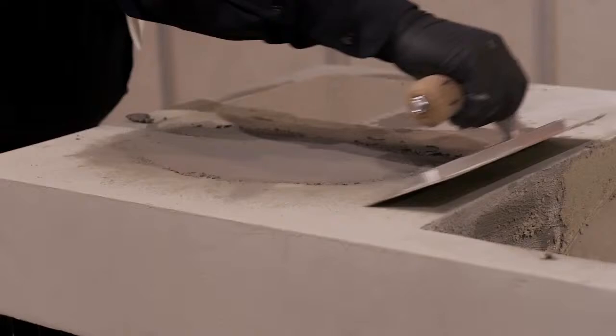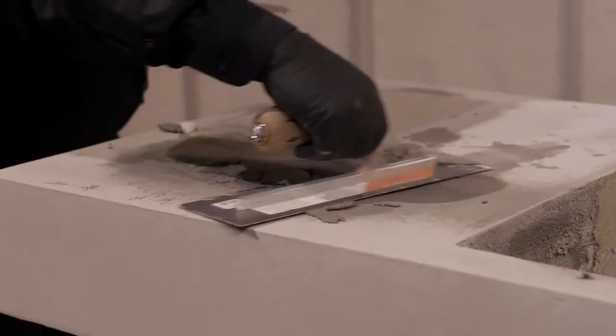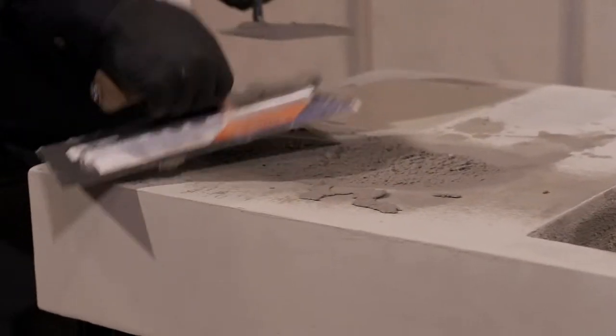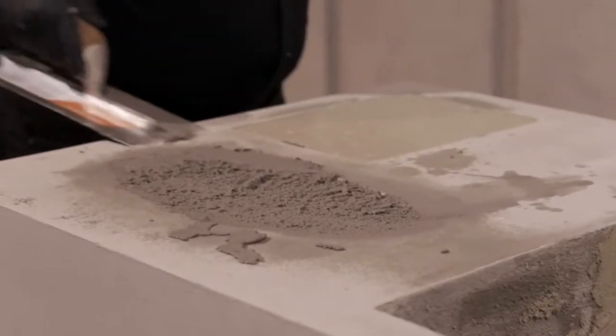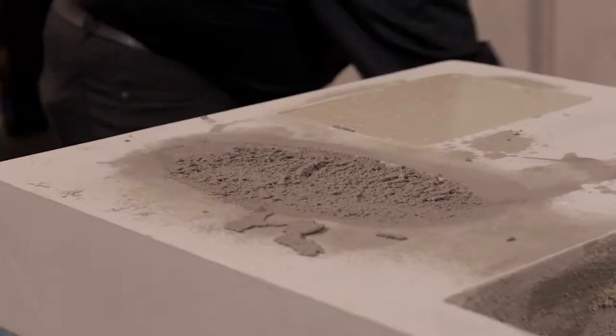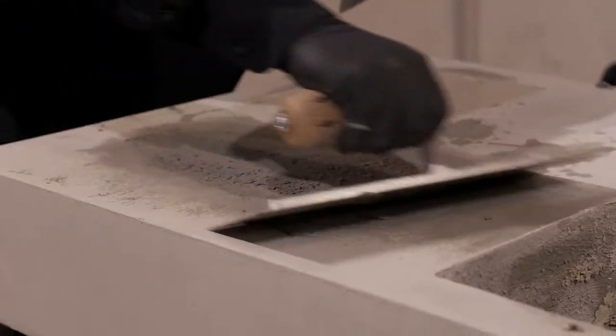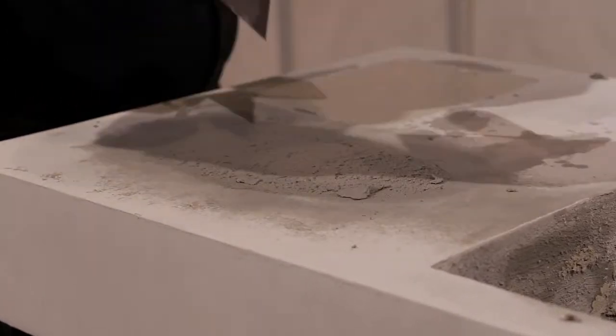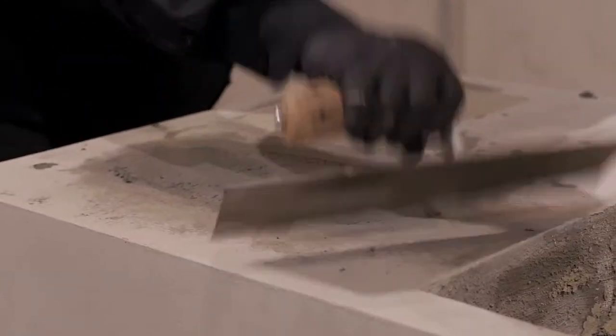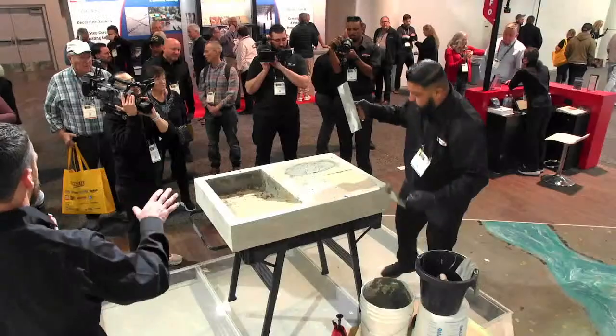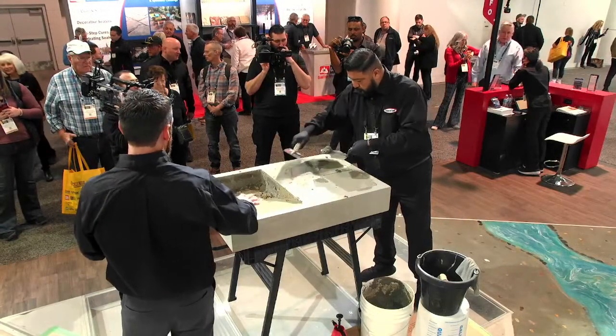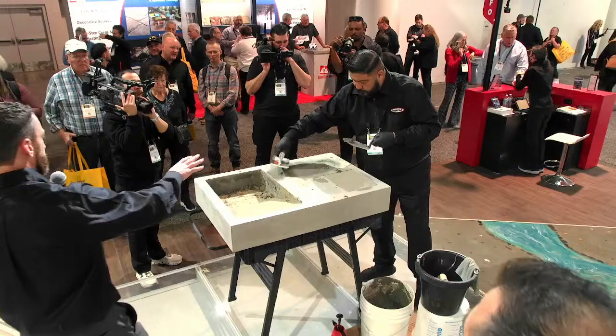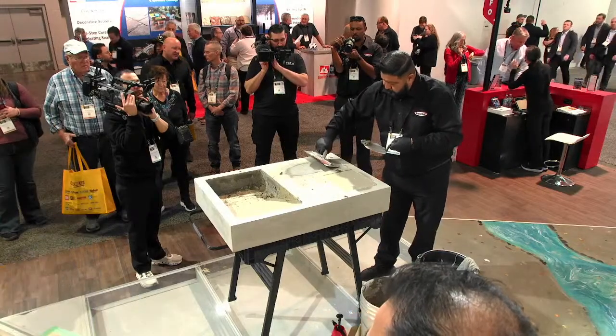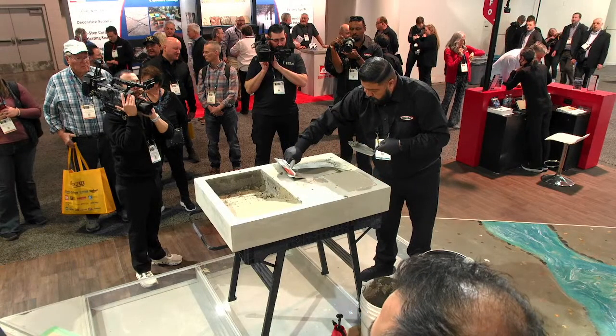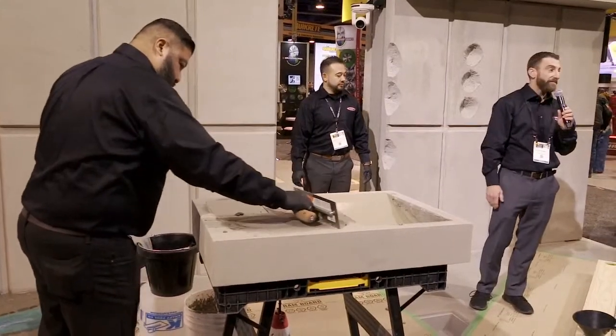And the compressive strength on this will exceed 4,000 psi in just 3 hours and 8,000 psi at 28 days. So still a very high strength material, but it is just a little bit slower to give that extra working time and for applications where you don't need that very high early strength. So again, if you need 1 hour strength, Cementall is the best solution. 2 hour strength or a little bit extra working time, Cementall Plus. Cementall Plus also contains the self-curing technology and is designed for high freeze-thaw durability.